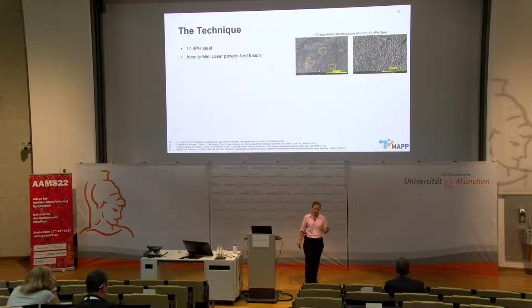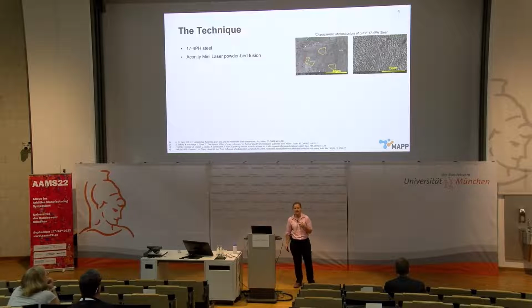Well, some time ago we developed a technique on 17-4 PH steel. So 17-4 is conventionally regarded as a martensitic steel. If you manufacture it or buy it in bulk conventionally, it will contain around 90 to 95% weight of martensite. And we found that when we build it on a laser powder bed fusion system, specifically here the Aconity Mini that we've got at the University of Sheffield,